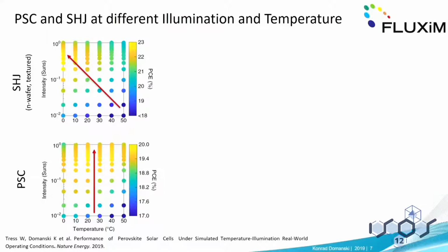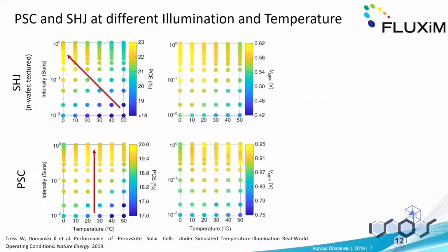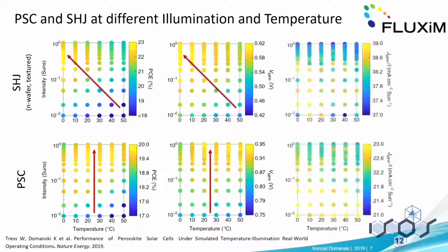But then the question was how they behave at maximum power point, because this is where we actually operate throughout the day. So we looked at the voltage at maximum power point, and for silicon, again, we see that it gets higher towards lower temperature and higher illuminations, up to around half a sun. For perovskite, again, the trend is the same as for efficiency. It gets better only with illumination. And then for the current,